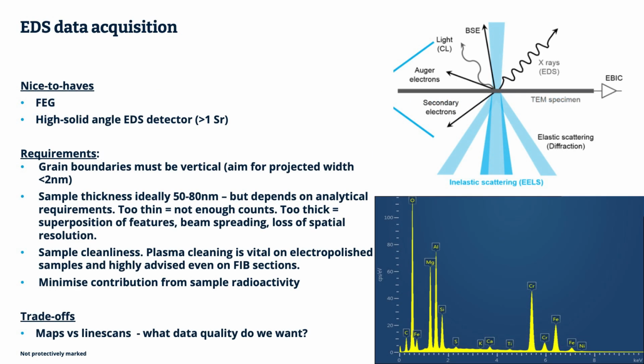On EDS, first of all, this is what happens in your microscope. The beam comes in from the top, interacts with the sample. We produce X-rays, backscattered electrons, photons. We get elastic scattering, which allows us to use imaging, like Jack was showing, and the inelastic scattering informs us also through the EELS technique. So let's look at what happens with X-rays.